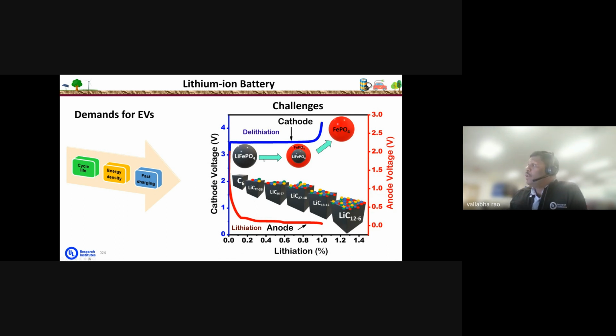If you look carefully, the deinsertion and the insertion of these lithium ions into the materials have different mechanisms and different processes. For example, on the anode side, when the lithium ions intercalate into the graphite, it transforms into different lithiation phases. Over the lithiation process, the volume can also change, which can hinder the initially formed SEI layer on the surface of the anode. When we operate this cell even at fast charging, these effects become even more pronounced, so it can reduce the performance of the lithium ion cell even faster.